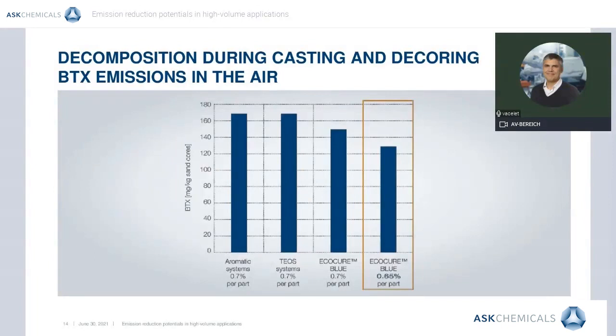Okay. The BTX, benzene, toluene, xylene, are formed during the so-called pyrolysis process. The thermal degradation of the polymer network during the pouring produces fragments, so-called radicals, which can react further, recondense into the sand, or evaporate. This process can be analyzed but never precisely predicted because, besides the binder, temperature gradients, transport phenomena in the sand-binder mixture, and so on, play an at least as important role.